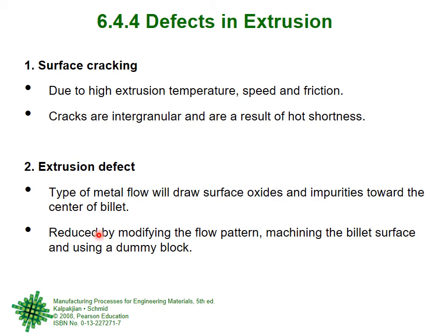They can, of course, be reduced by modifying the flow pattern, by machining the billet surface to a very high surface finish, and by using a dummy block. We have shown you when we were showing the equipment that a dummy block is sometimes used between the ram and the billet material, so the direct contact between the ram and the billet does not take place. So this is extrusion defect.